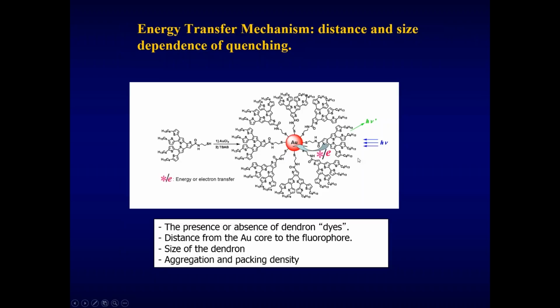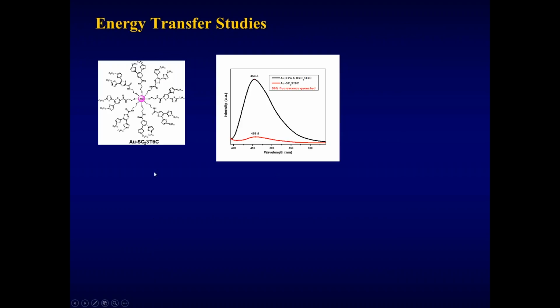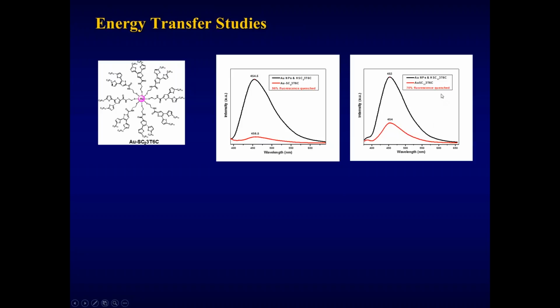So why are we interested in these materials? Well, the gold nanoparticle basically has an absorbance of around 550 nanometers, whereas the terthiophene and the heptathiophene have fluorescence around 500 to 550 nanometer region. So the point is, by overlapping the absorption and the fluorescence, energy transfer mechanisms can actually be elucidated as a function of distance. So just to show you the effect, here is a terthiophene with 2 carbons.